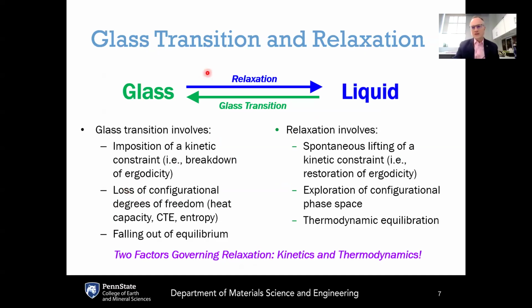This also defines these two inverse processes. The glass transition is the process whereby a liquid is kinetically frozen into the glassy state, and the opposite process is called relaxation, which involves the relaxation of this non-equilibrium glassy state to the liquid state. And these are opposite processes in that the glass transition involves imposing some kinetic constraint on the system. Imposing that kinetic constraint causes a breakdown of ergodicity, going from the ergodic liquid to the non-ergodic glassy state. When that happens, there is a loss of the configurational degrees of freedom. So the liquid was allowed to explore many different configurations. Those configurational degrees of freedom are lost when you impose a kinetic constraint on the system, freezing it into just either one configuration or a small number of configurations.